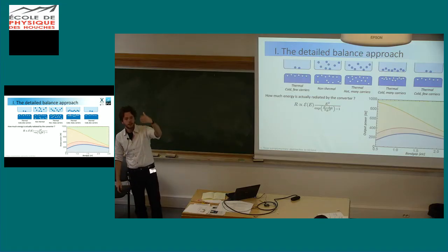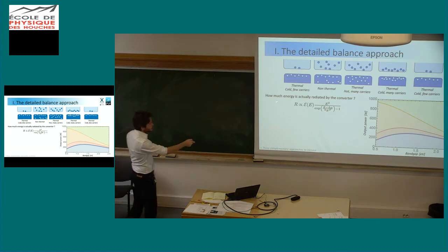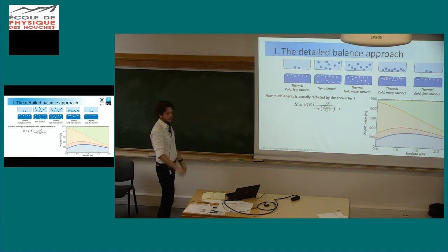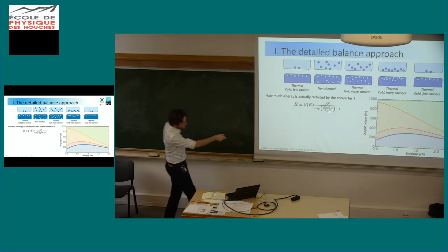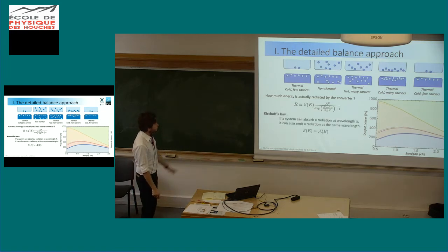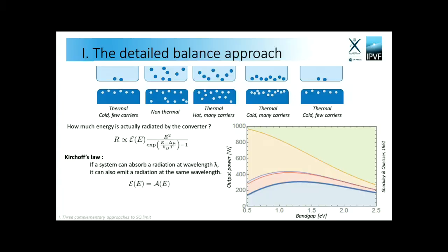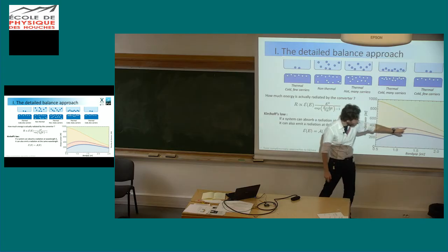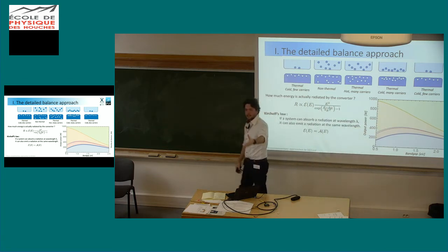Now this, of course, is related to the photoluminescence talk which Laurent gave us the other day, and it's related to the generalized Planck law. So what you emit is related to the emissivity of the system times the Fermi level splitting, which is really the voltage. Okay? So I'll skip on how this is related to the absorptivity, but if I include this now, I will put it here to make it visible. This violet curve here would be the energy which is lost due to radiation.